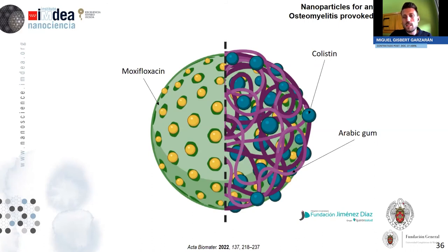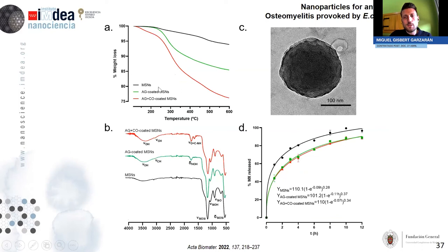But luckily, as we will see now, the use of a slightly lesser amount of Arabic gum just slowed down the drug release, which is not so bad, by the way. But the important thing is that it endowed the nanoparticles with affinity for the bacterial biofilm. So the biofilm, very briefly, is a state of the bacterial growth in which they are basically confined within a polymeric mesh. In summary, in that state, they are resistant to antibiotics and they are more difficult to eliminate. Okay, so we characterized the nanoparticles using the same techniques that we have been using so far.